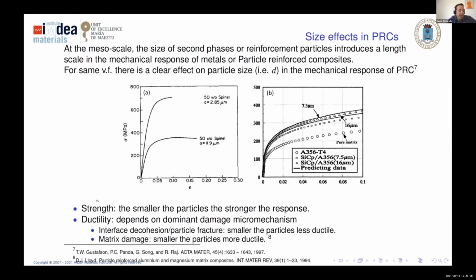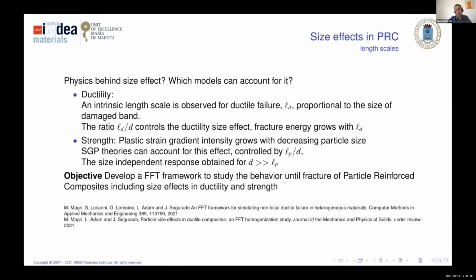And the type of size effect is: the smaller the particle, the stronger the response, but we also have an effect in ductility. This effect is not so clear, but it depends on the dominant damage micromechanism. So if we have interface decohesion, the smaller particles produce a more brittle behavior, but if everything is ruled by matrix damage, that's what we're going to study, and this might happen at high temperature, then the smaller the particles, the more ductile the material. And what's the physics behind? And what models do we have if we want to account for this?